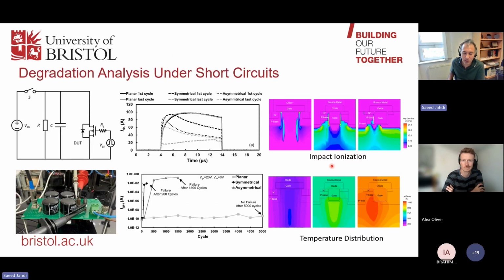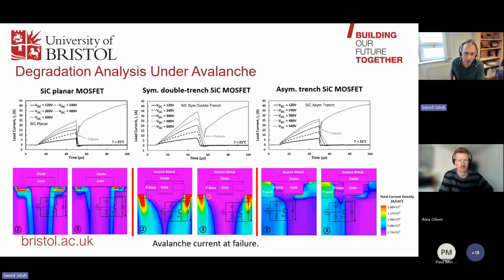In terms of EV chargers or EV drivetrains, one of the key parameters is, for example, short circuit. We have done measurements on that and developed TCAD models for it, and we can see, for example, that planar devices perform significantly better than the existing symmetrical or asymmetrical trench devices when it comes to short circuit reliability. This is obviously the state of the art of the devices for the past few years, but things are improving, so hopefully trench structures will be able to catch up with the planar ones in that sense too. The same applies in terms of avalanche. In terms of avalanche, trench devices, both symmetric and asymmetric, are not too bad compared to the planar devices, but there are still bottlenecks that need to be addressed.